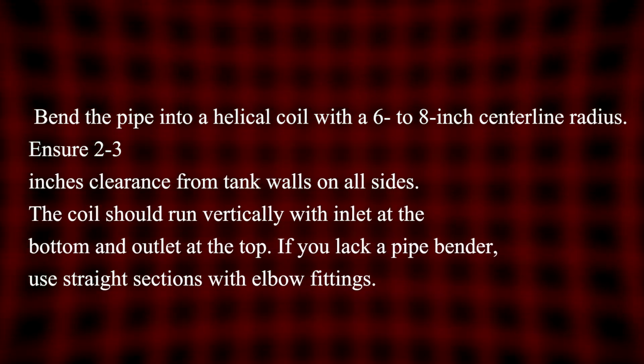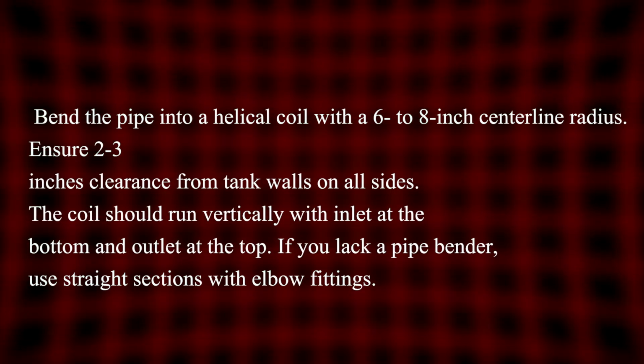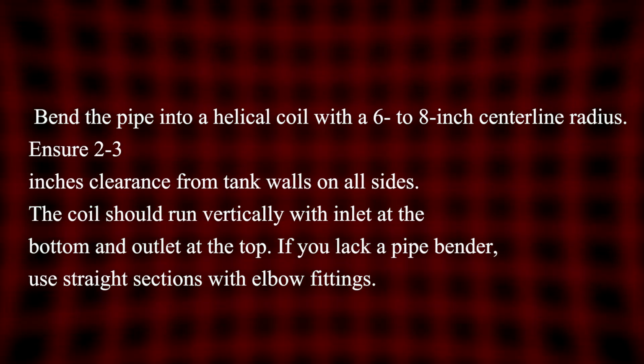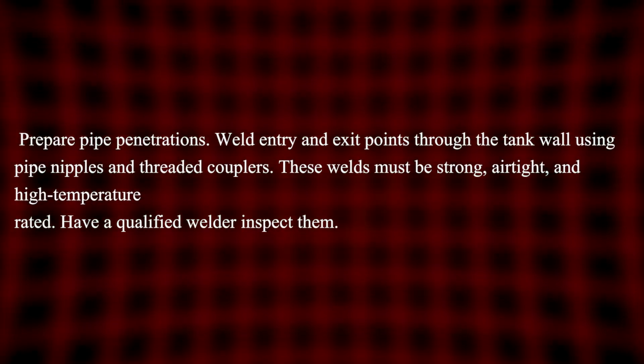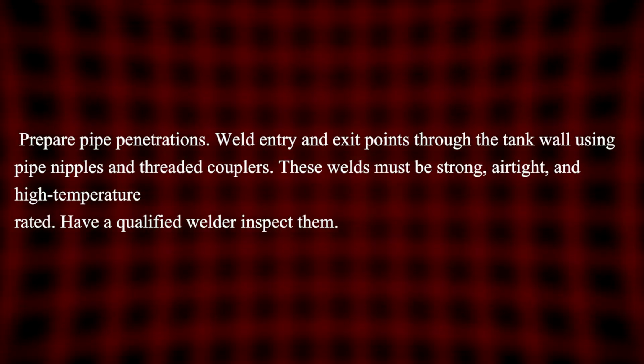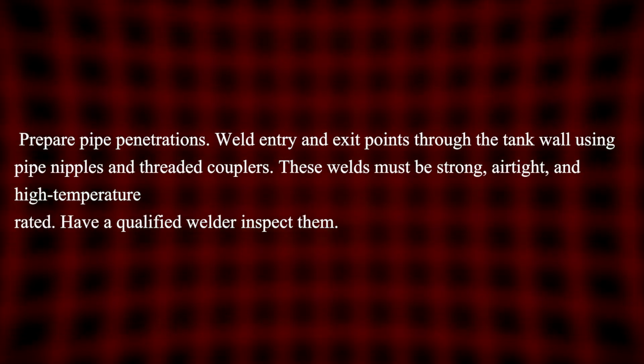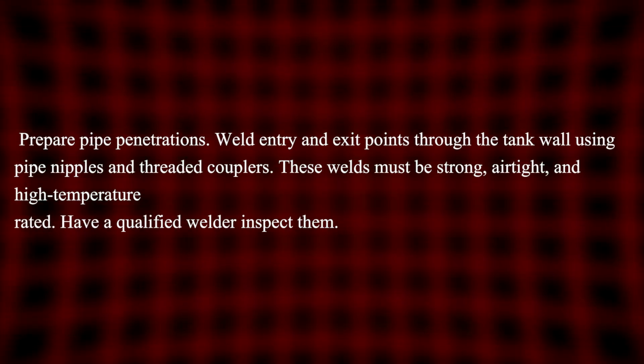Ensure 2 to 3 inches clearance from tank walls on all sides. The coil should run vertically with inlet at the bottom and outlet at the top. If you lack a pipe bender, use straight sections with elbow fittings. Step 3. Prepare pipe penetrations. Weld entry and exit points through the tank wall using pipe nipples and threaded couplers. These welds must be strong, airtight and high temperature rated. Have a qualified welder inspect them.